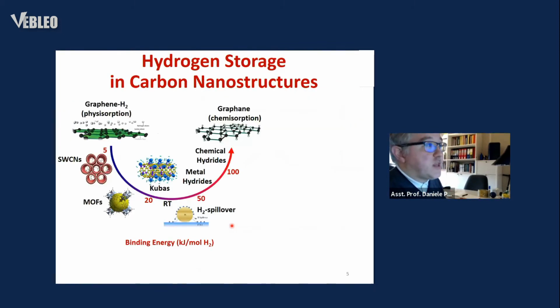If we focus on carbon nanostructures, they are able to store significant amounts of hydrogen, but the binding energy, depending on the storage mechanism considered, is too low or too high for practical applications. In the first case, hydrogen is weakly bound to a porous carbon network with a physisorption mechanism with typical binding energy of the order of a few kilojoules per mole of H2. The physisorption process needs rather low operating temperature, below 100 K, unsuitable for application.